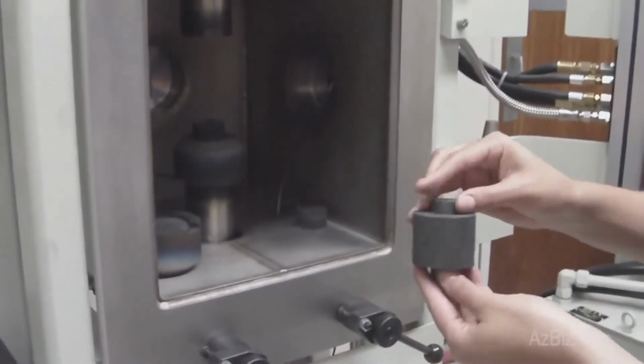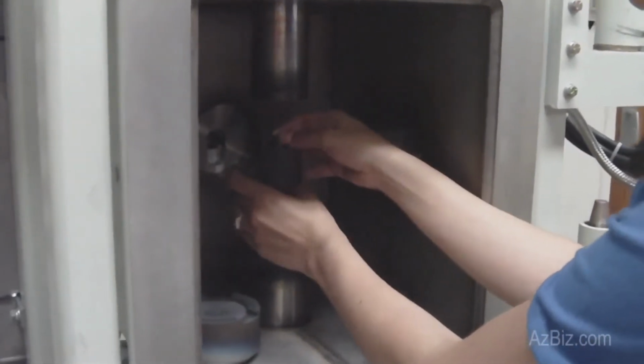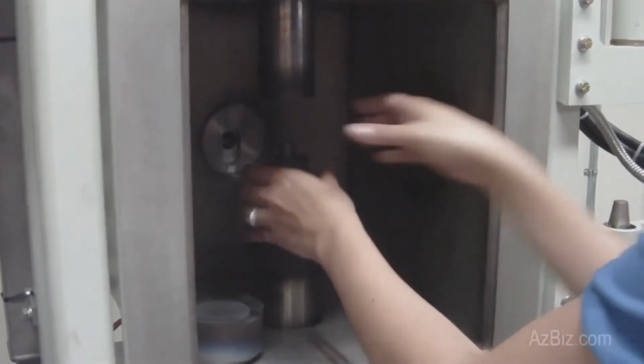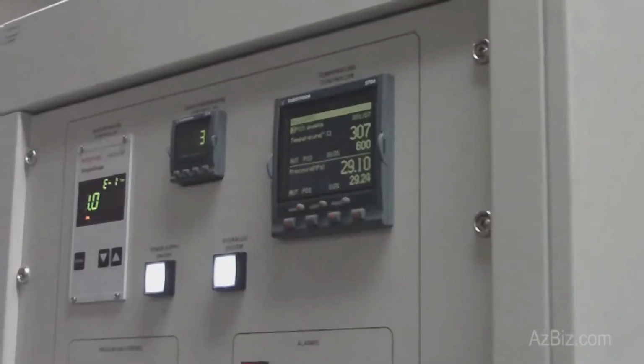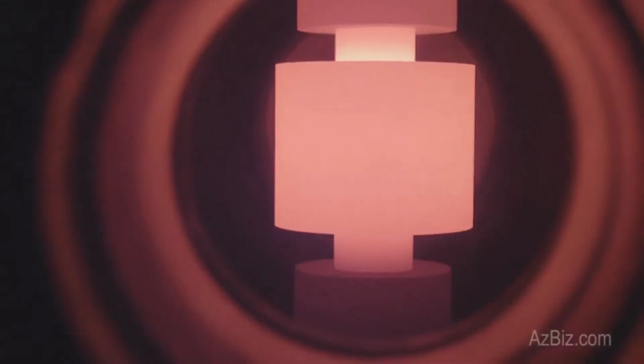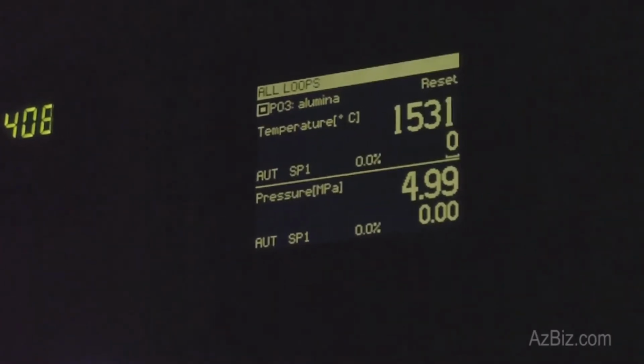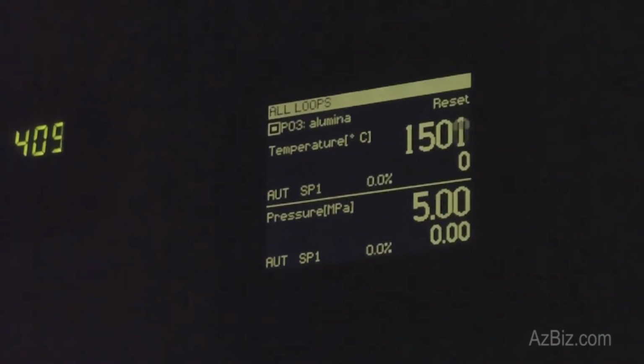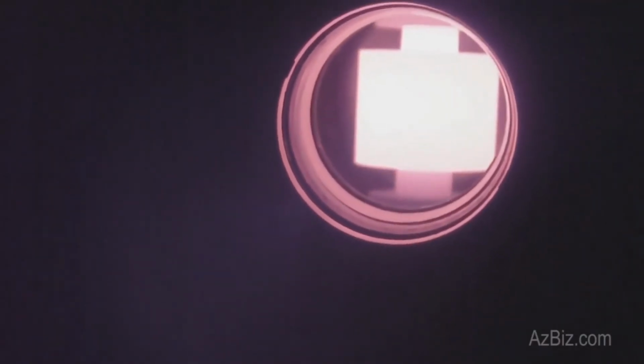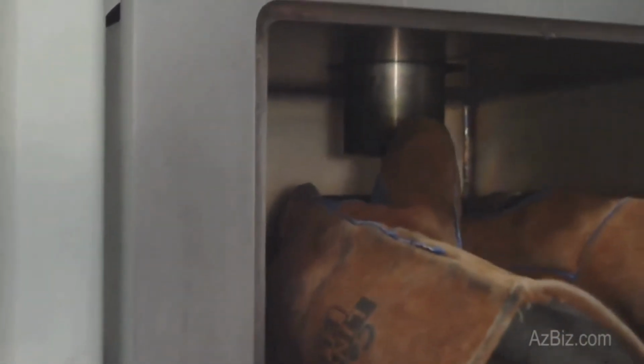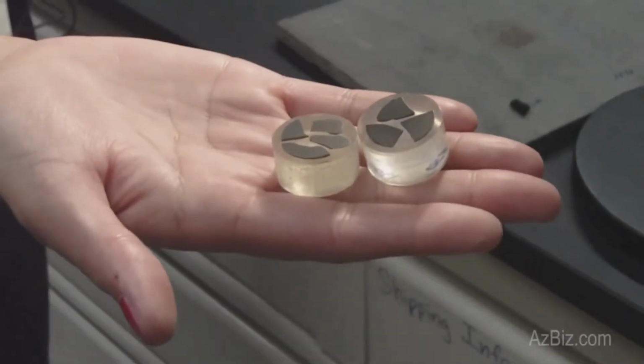The type of furnace we have in our laboratory is called a spark plasma sintering furnace, and it is unique in the sense that conventional ceramic processing uses a furnace that heats up the material from the outside. Your sample sits inside and radiant heating basically heats the material. The difference with our furnace, which is still rather novel to the field of ceramic processing in 2010, is that it uses a DC current that pulses through the material and consolidates it in a matter of minutes. The advantage of spark plasma sintering is that we can basically retain that structure instantly and limit all of the grain growth that you would see in a conventionally processed ceramic.